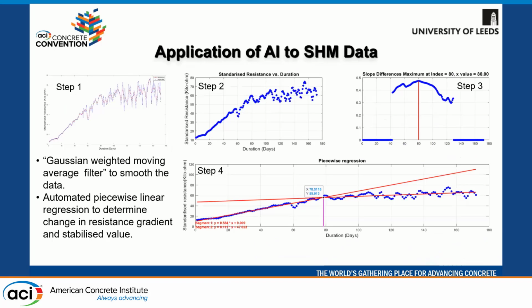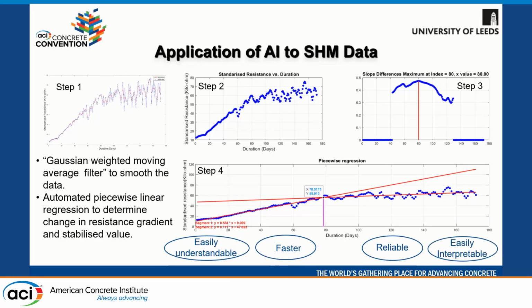That is why we used an automated approach to determine change in resistance gradient and stabilized value. The first step was to use a Gaussian weighted moving average filter to smooth the noisy data, so the noisy data is compressed, keeping the original trend. The second step was to use an AI-based application similar to k-means clustering, which divides the total data into two segments and identifies the maximum slope difference from the data. In step 4, it shows the ultimate breakpoint, which depicts the stabilized value of resistance and time taken to stabilize that resistance value. The slope of segment 2 here shows that resistance is still increasing, but at a slower rate. So this approach is easy to understand, faster, reliable, and easily interpretable.